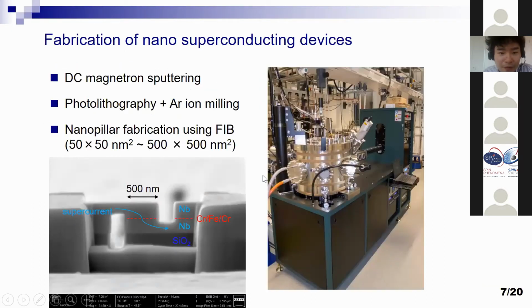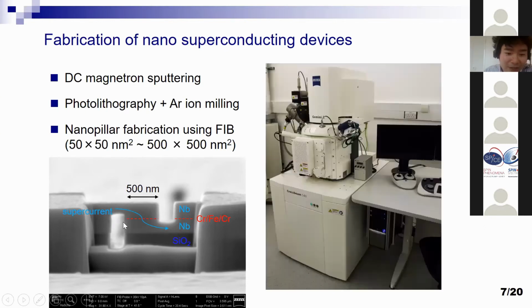And we make this kind of device using conventional magnetron sputtering and focused ion beam patterning. We deposit the layered structure on a silicon dioxide substrate. Here the black region is silicon dioxide, and we have thick top and bottom niobium layers. We cannot see it from this SEM image, but there are thin magnetic layers, chromium and iron chromium, in the middle. If we pattern this film using FIB, we make two side cuts here and here. Then we can force the supercurrent to go through this magnetic barrier layer, and we can observe the Josephson properties of these magnetic Josephson junctions.